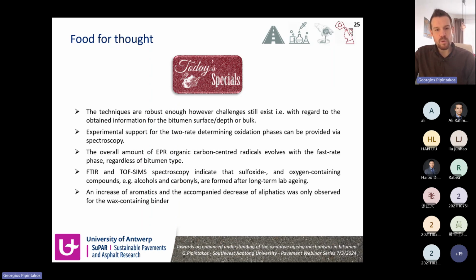What is important is that we use several experimental techniques, some of them not so often utilized, let's say, for bitumen. But we should always take care that these give different information sometimes. And with different information, I mean that they, for example, give information at different depths of the bitumen, comparing, for example, the TOF-SIMS with the FTIR.